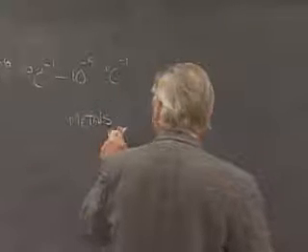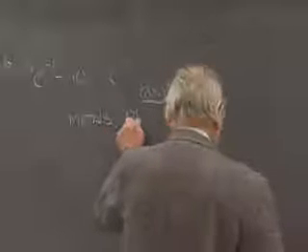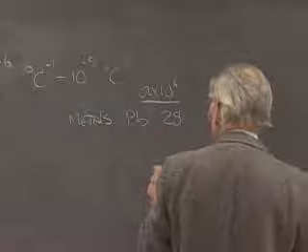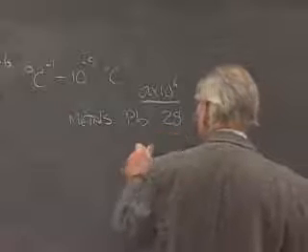But for metals, and I'm giving you a single number now because these are averages for polycrystalline materials. The value of alpha times 10 to the 6th. For lead, a low melting metal, is 28, 2.8 times 10 to the minus 5.